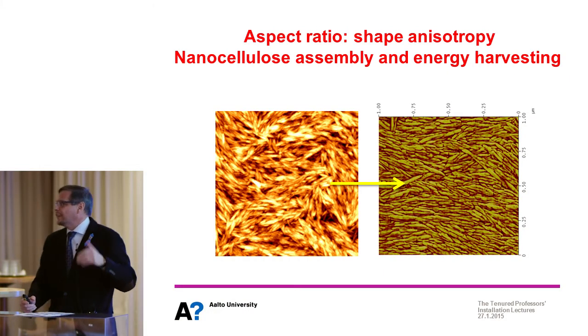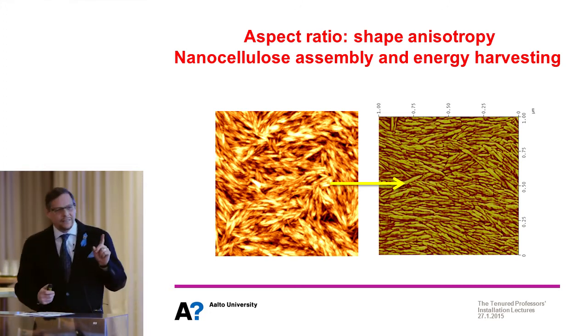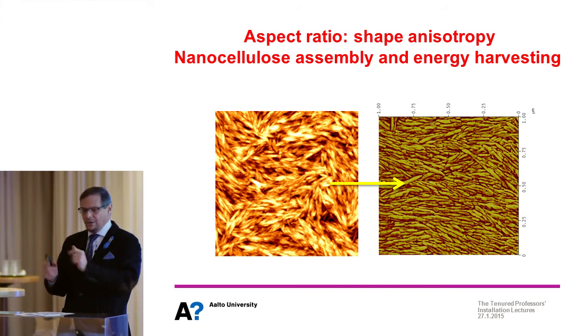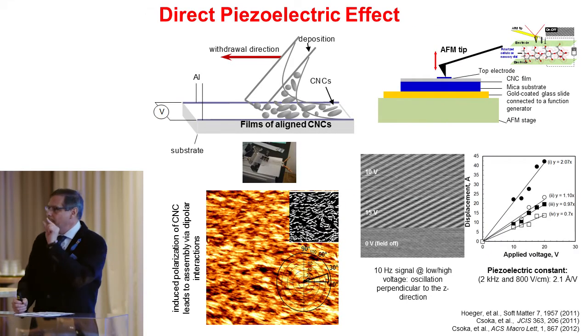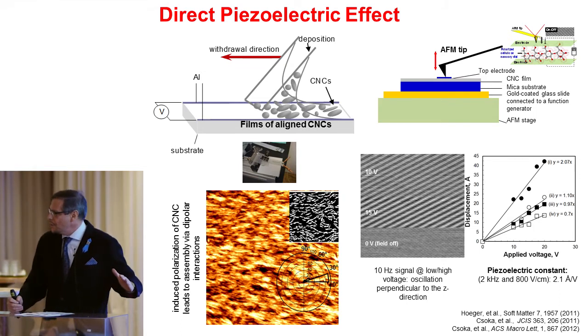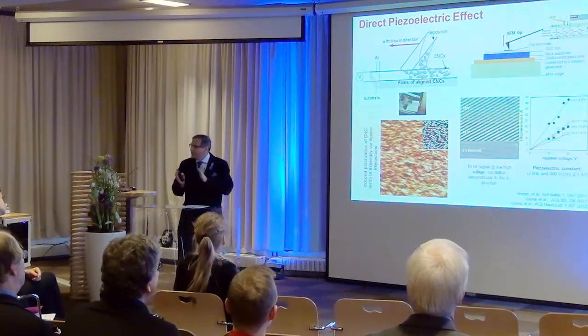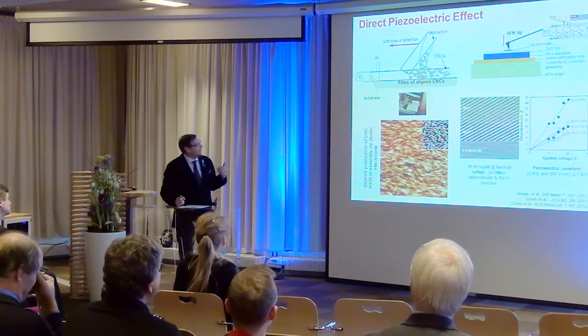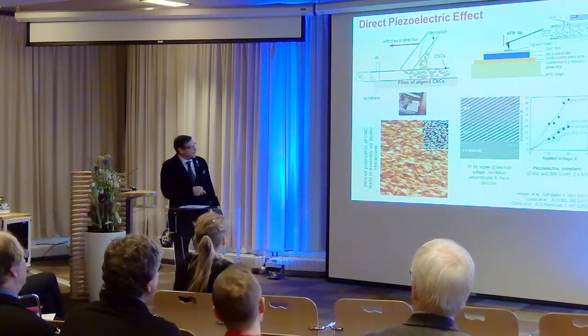So now I'll tell you about four different types of asymmetries that we have exploited to produce new materials. The first has to do with the aspect ratio. The particles are not spherical — they are long and thin. This is extremely important because you can think about those units being able to assemble in an ordered fashion, making structures that are aligned. We have tried to do just that: align those building blocks that come from the tree — nanocrystals. We do that by putting a nanocrystal suspension on a surface and shearing that suspension. As a result, because of the high aspect ratio of those particles, they will align. And if you apply an electric or magnetic field, you have a very good alignment and packing of those particles.